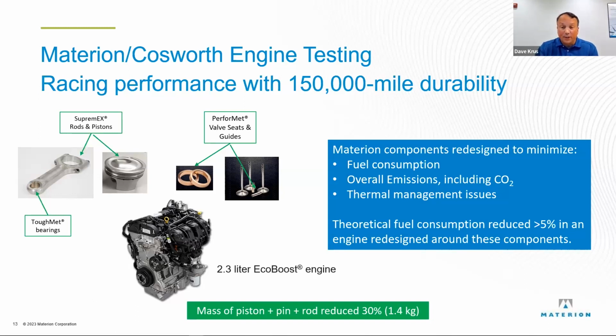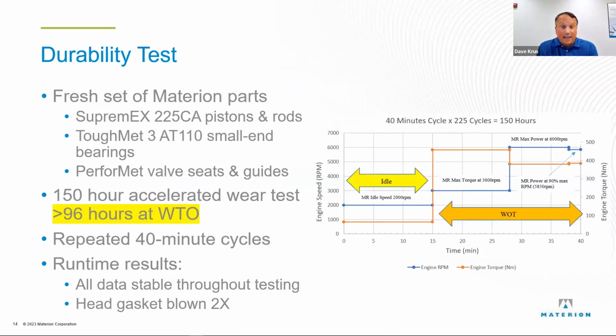But going on to the durability test, this is going to show that these materials are set to last. We put a fresh set of those parts in, or they put a fresh set in, and did a 150-hour wear test. And that's 15 minutes at idle, followed by about 13 minutes at max torque, about 10 minutes at max power, and a couple more minutes at 90%. Rinse and repeat, 225 times. So that gives you 96 hours at wide open throttle.